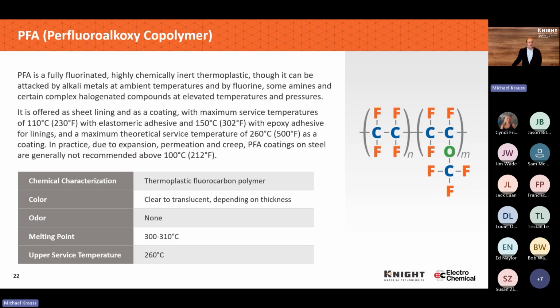When you look at PFA, this was developed after FEP, and the upper service temperature bumps up a little bit higher. So this was developed to be a melt processable version of the original Teflon PTFE material. Looking at the chemical composition, again, no hydrogens. So you see that everything's been fully fluorinated. All the hydrogens are substituted. That branched material, the copolymer, is a little bit larger than the FEP unit. And the branchings would allow them to get to a bit higher temperature range here.